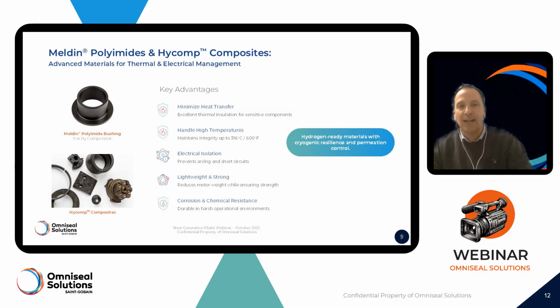For the Hycomp composites, the range is from minus 140 degrees C to 320 degrees C, and mechanical strength can go up to 710 megapascal. Key advantages for these materials are the light weight compared to metal components while maintaining strength, so up to 40% lighter than aluminium and up to 75% lighter than stainless steel and titanium. They also have very good dimensional and mechanical stability at elevated temperatures. And thanks to this, complex parts can also be machined out of these materials.